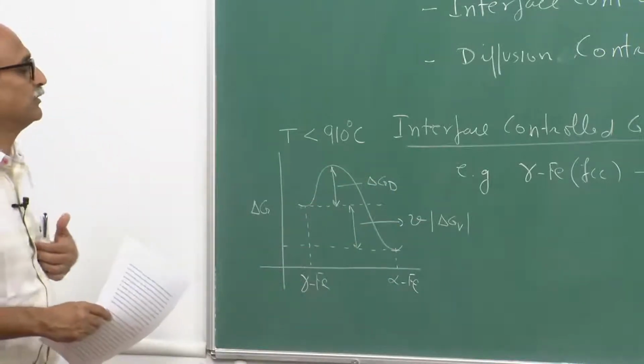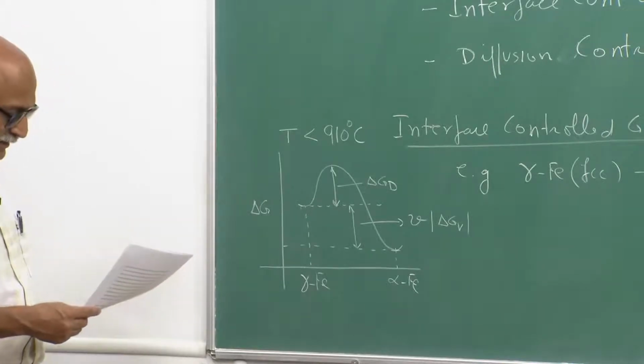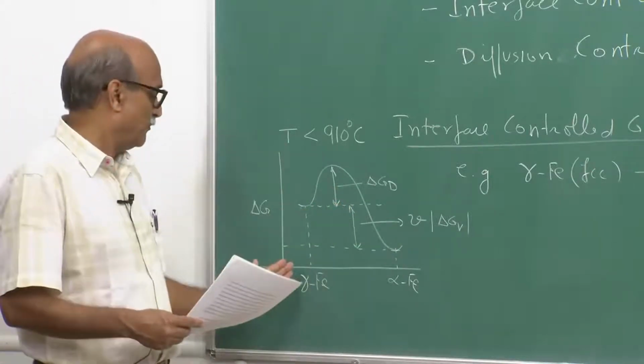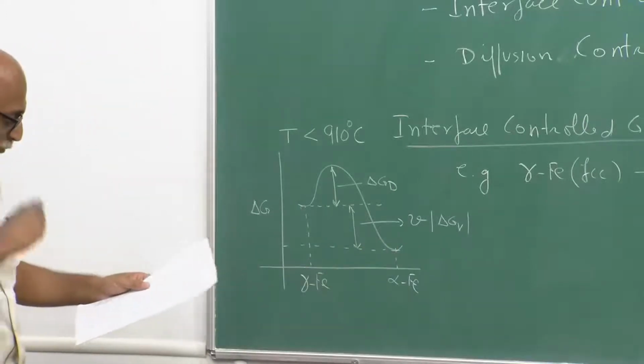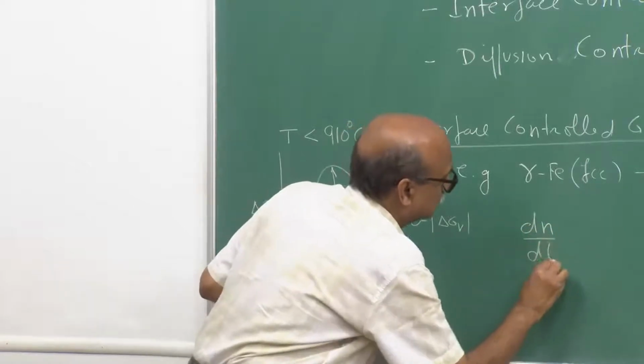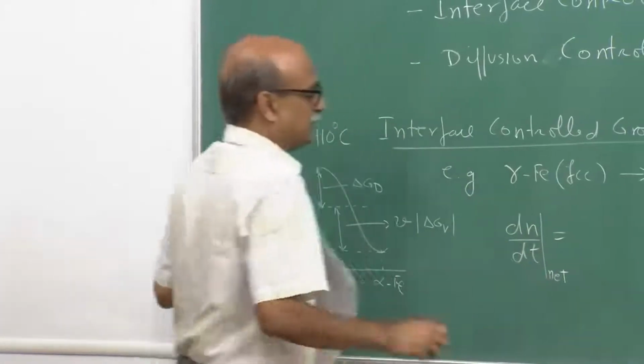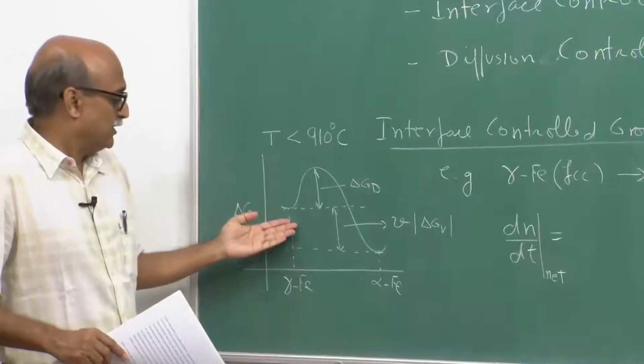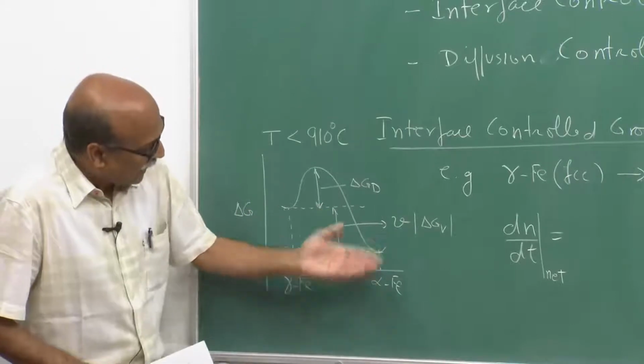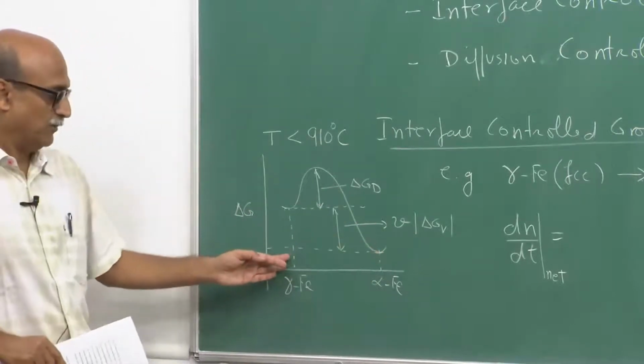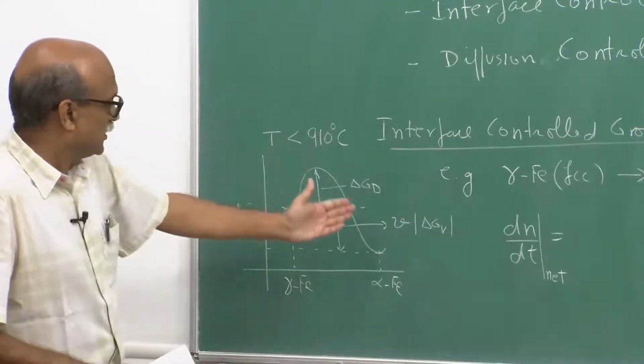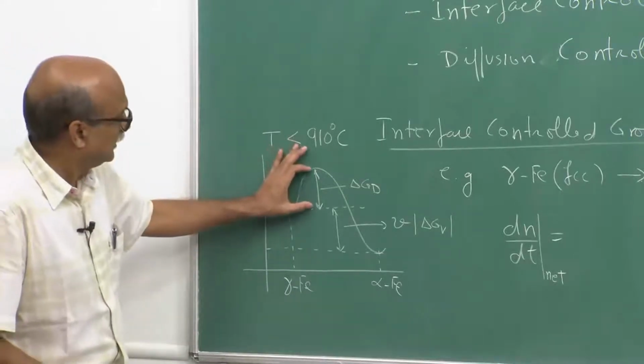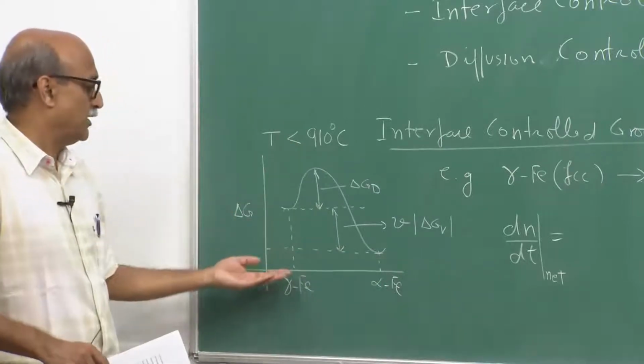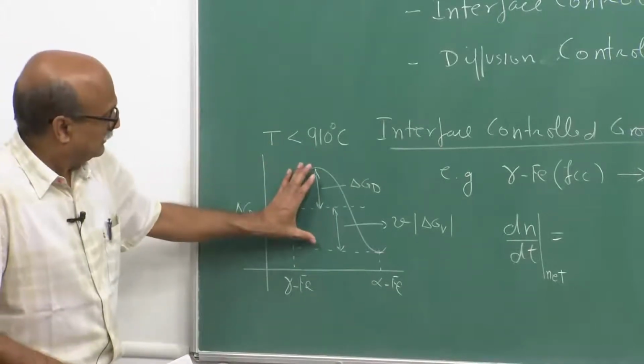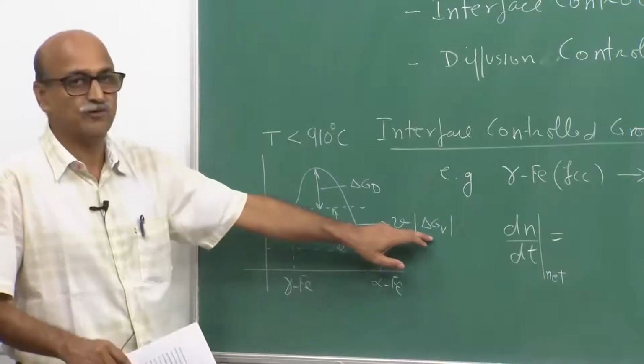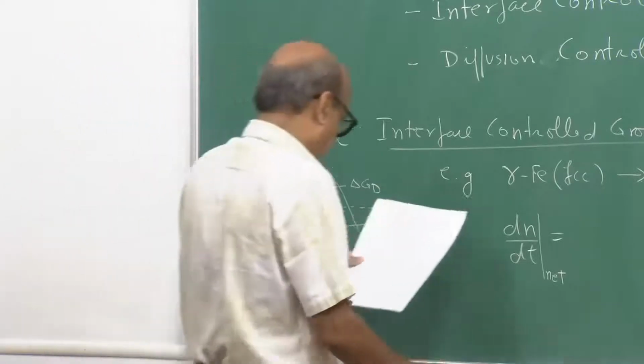Now, if we wish to compute or rather estimate what is the net jump rate of atoms from gamma to alpha, let us call that dN by dt, the net jump rate. The net jump rate would be the difference between the forward jump rate of atoms from gamma to alpha minus the backward jump from alpha to gamma. So, for atoms to jump from gamma to alpha, the energy barrier is only delta GD, while for the atoms to jump from alpha to gamma, the energy barrier is the sum total of delta GD plus V times the absolute value of delta GV. So, writing this down, Ns,